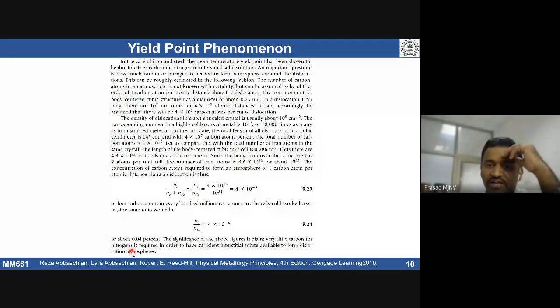After that, Johnston gave a very nice explanation of why there should be a drop, because of instability in the strain rate of deformation within a material and externally, so that can lead to a drop in the stress. Now this has a problem, because if you see a yield point phenomenon in a material, that can lead to formation of an irregular, uneven rough surface.